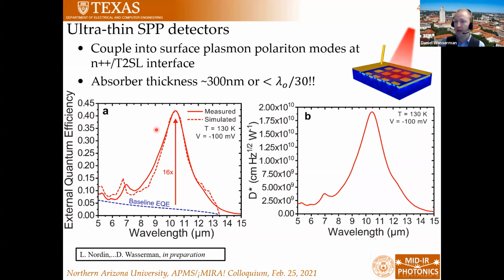And this has real applications for detector figure of merit. If you look at the D star, which is the detectivity, which is the measure of a detector, we are in the 10 to the 10. So this is state of the art D star at temperatures like 130K. These detectors are essentially beating state of the art. They're beating what's available commercially. And the reason is because we can go very thin without sacrificing our external quantum efficiency, but we decrease the noise, the dark current associated with the detectors. And I should note that if we grew this material in just a traditional detector structure, it would take 7.5 microns of material in order to get this same external quantum efficiency. And that's assuming perfect collection, which is unlikely in this material system.